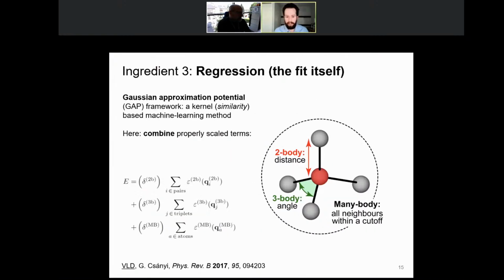So yes, this is this kind of combined model that we're making. There are two different things. One question is, how far out does your descriptor go? How many environments do you have to take into account? In this case, we've used a cutoff of 3.7 angstroms, which gives you the first and the second peak in the pair distribution function. So it includes the next nearest environments, and everything up to that cutoff is being included, which gives you a dozen or so contacts probably.